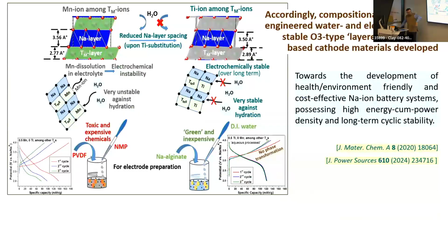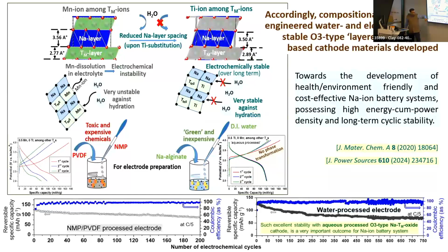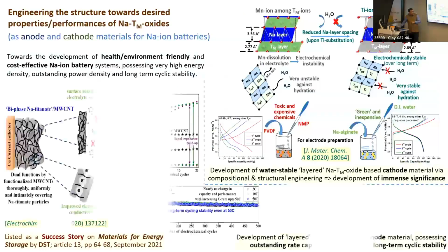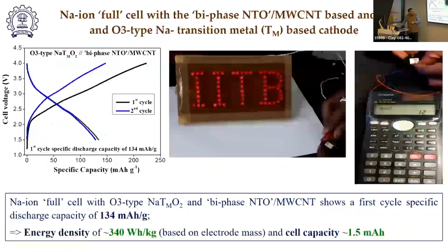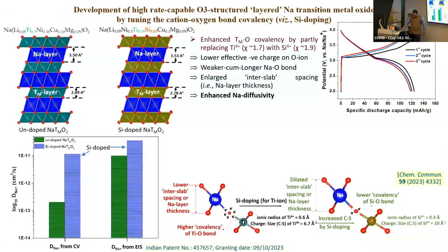Now, this shows just one example of an aqueous process layered transition metal oxide. So this material was highly water stable. It's very much water stable. So one could make the cathode using water as the medium, not NMP, and it cycles reasonably well. Of course, one has to make it more stable. So this is an example of, I think, full cell, forget it. Yeah.